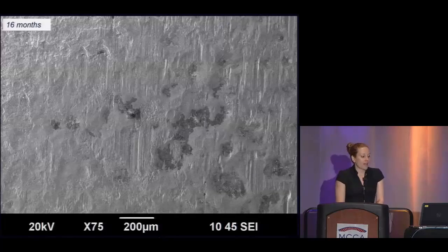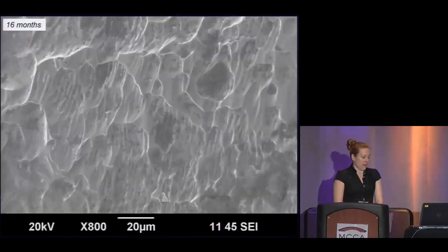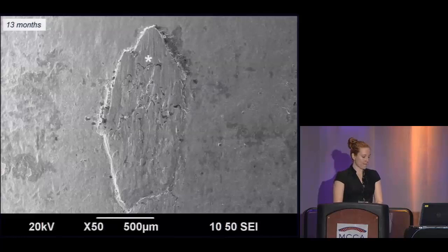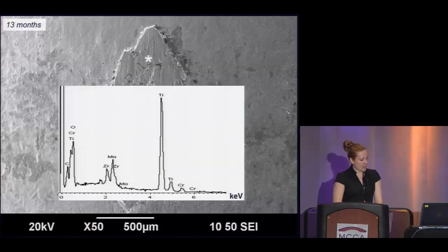Scanning electron microscopy reveals severe fretting and corrosion of these cobalt chrome implants. At a higher magnification, we can see the scalloping nature of the corrosion and the dissolution of the alloy. Here, in an example of adhesive transfer, we can see the beta titanium has adhered to the cobalt chrome modular neck. An energy dispersive analysis reveals that this is indeed the beta titanium.